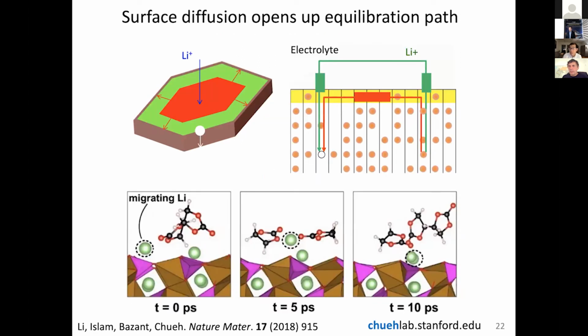So it turns out that lithium can move efficiently in this material on the surface. So within the bulk of the material, lithium has no way to travel left and right in my schematic. Lithium can only travel left and right if it comes out of the particle and then enters in another location. This is the standard bulk behavior of the system. But it turns out in this material, there is a surface diffusion path where lithium can move very efficiently at the interface of the electrolyte and the lithium iron phosphate, at a rate that is much faster than in the bulk of the material. And this is actually due to an assistance from the solvent molecules like ethylene carbonate, which basically allows the lithium to hop between one-dimensional conduction channels. So essentially what is happening here is you are taking a material which is insulating in plane in the bulk, but is highly conductive on the surface. And that allows lithium to basically phase separate within one particle.